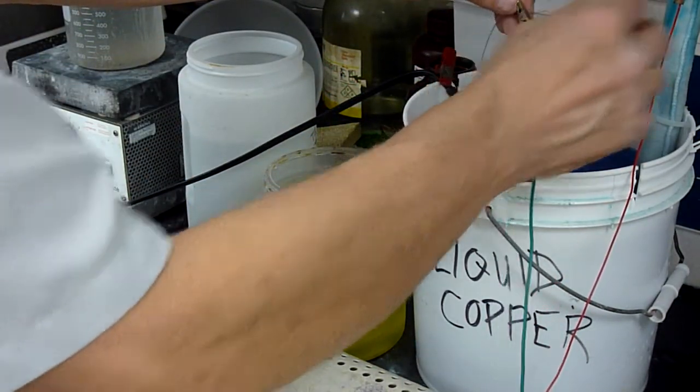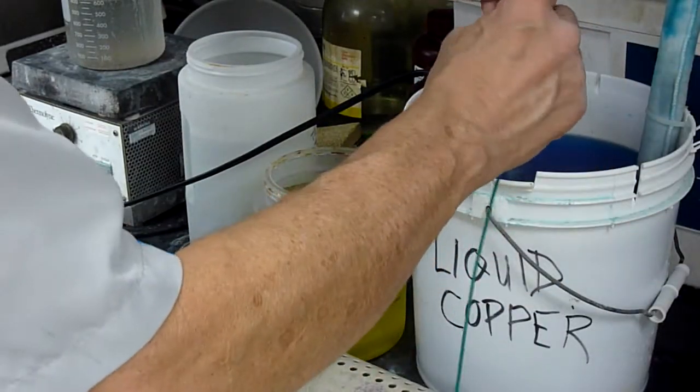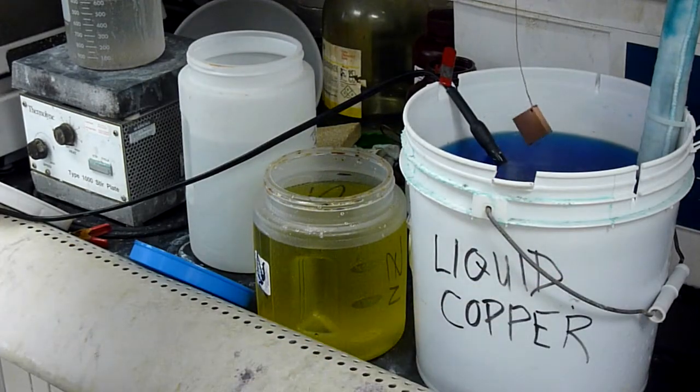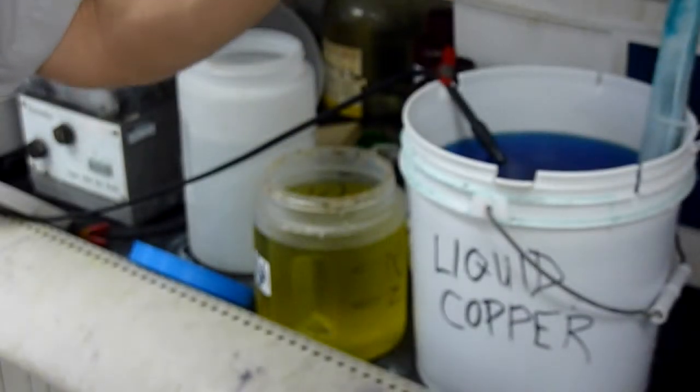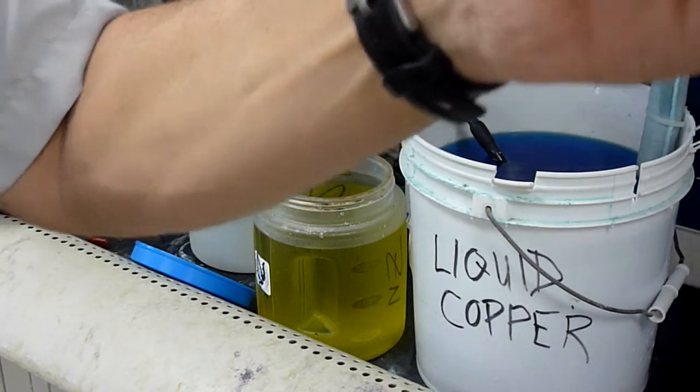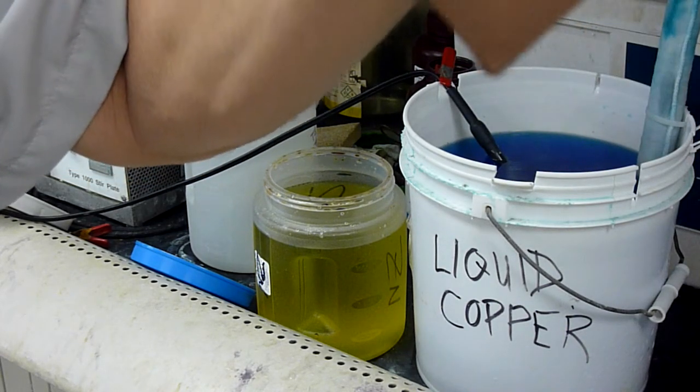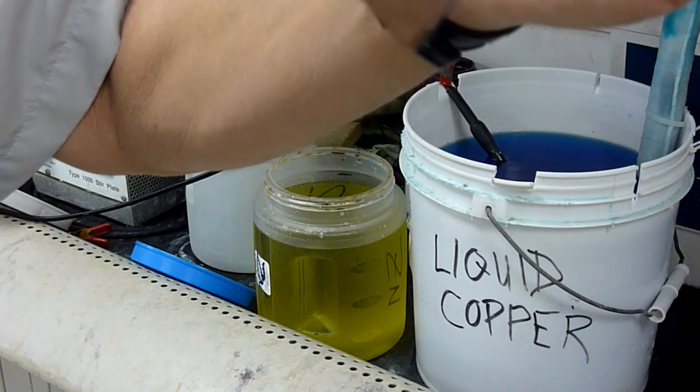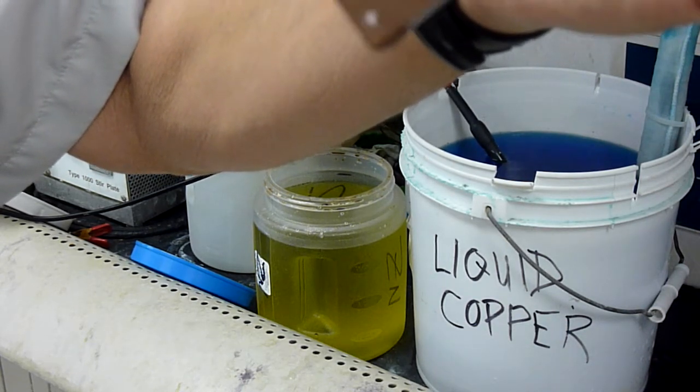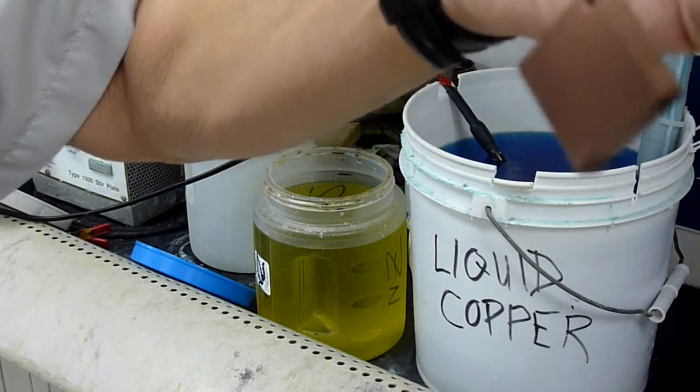Okay, so I think we're done at this point. I'm turning the current off. So that's a little bit on the dark side for copper plating. I might want to adjust the current density a bit based on the state of the bath, this two-year-old bath. And it might be that when we get heated up to normal temperature, which is on the order of 50°C, that we'll get a better result. But this is not terrible.